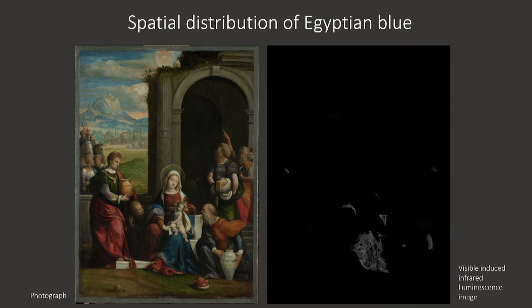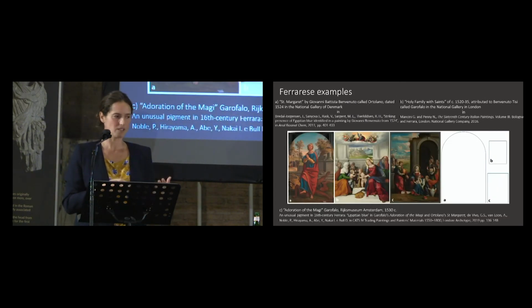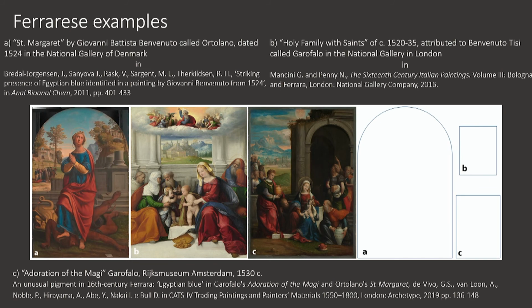So we turned to VIL, visible-induced luminescence, like Egyptian blue scholars do, to visualize the spatial distribution and the use of the pigment. And another little discovery was that it was not confined to the main figure of the Virgin and the main compositional group, but also used for minor details in the background, like, for example, the shawl of this figure there on the far right. So, of course, we dove into literature and found that there were two other Cinquecento Ferrarese examples already published. And so with our Garofalo, this makes a nice group of paintings that are linked somehow by geography and date.